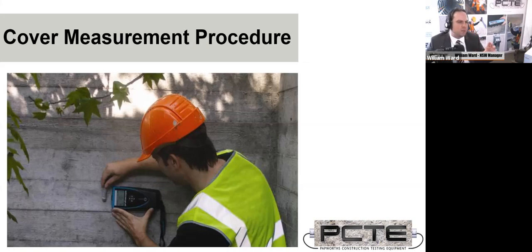Now, in both of those circumstances, the procedure would be to actually set up a mock-up and adjust your cover meters to give a correct measurement for that environment. You've got adjustments, particularly with the Profometer cover meter, where you can give it a calibration setting. You can say, we know this is 50 mil down, please set up my settings to measure correctly. And when you've got something more complicated than a conventional single layer of reinforcing steel, it's very useful to use those calibration settings. We'll come to that in one of my case studies. But once you have something which makes it more difficult, you need to be taking some measures to adjust your machinery. So let's go about procedure.